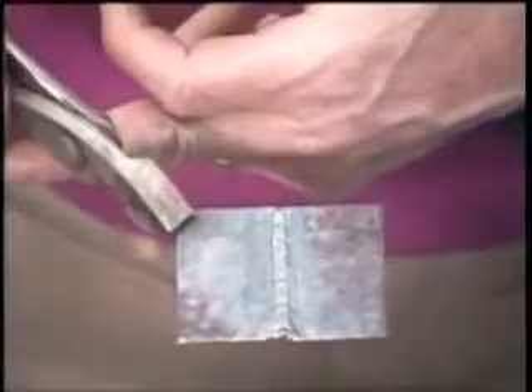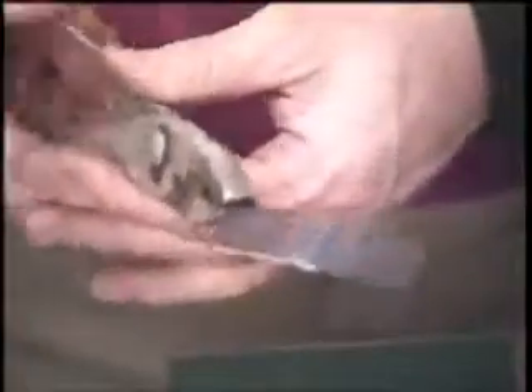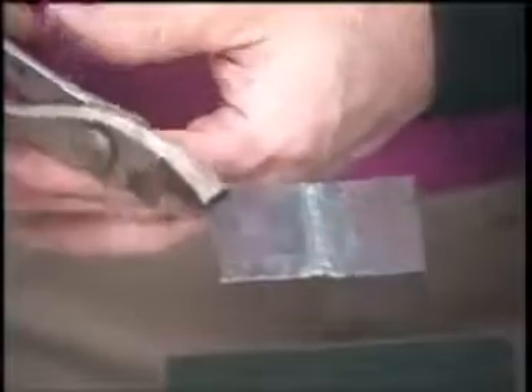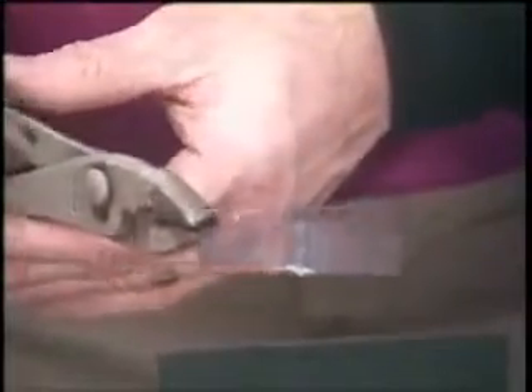Now, on that real thin sheet metal right here, you can see just how nice a bead you get. It's a very flat weld, so you have very little to grind off. Notice also just how little distortion you get, even on a small piece, while at the same time giving you 100% penetration in case you want to come back and grind that off right there. It does an excellent job on that thin sheet metal.